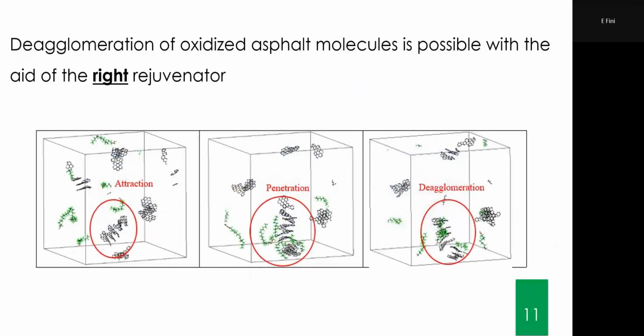And here are some of the results of the simulation. We basically built the asphaltenes and let them aggregate after aging. In the simulation box, you can see this circle here. And as the rejuvenator broke them apart, they became intercalated into that asphaltene structure. So now you see the green lines. Green molecules are the rejuvenator that are getting inside these asphaltene nano aggregates and breaking them apart.